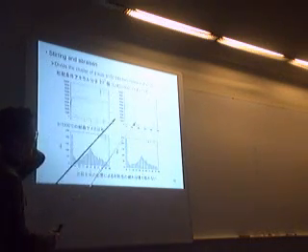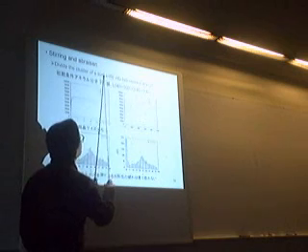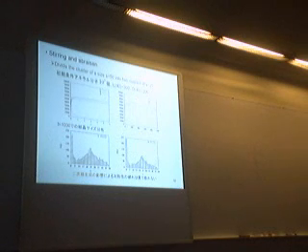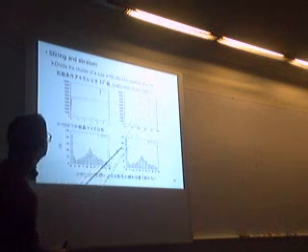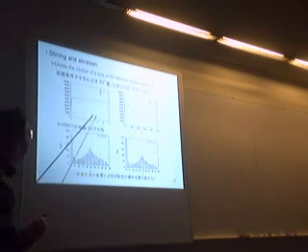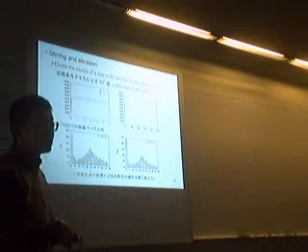And if the crystal grows up to a size 50, then in order to simulate the abrasion, you divide this size 50 cluster into 2 clusters of size 25. So the number increases. But there is no chiral breaking. L and D almost keep their number. So no chiral symmetry breaking or ee enhancement is observed.